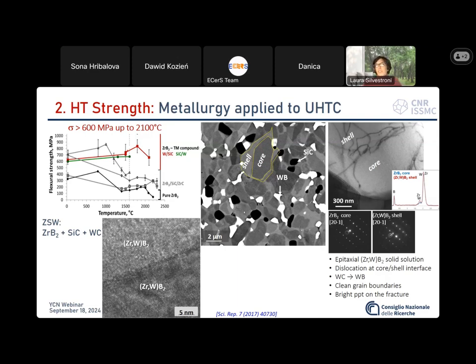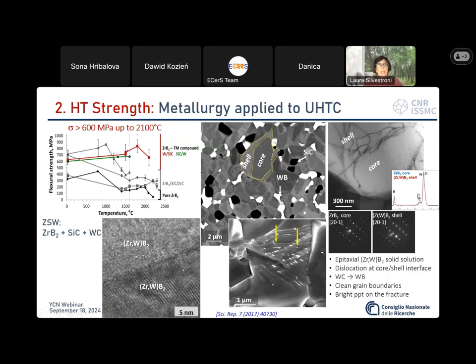As main microstructure features, it was fully dense with clean grain boundaries and a mean grain size around 1 micron, nothing special. The grains were featured by a core-shell structure with a pure zirconium diboride core and a solid solution around the core containing tungsten. Most of the tungsten carbide was converted into tungsten boride phase due to the reducing environment. And in addition, we noticed on the fracture surface that we detected these bright elongated particles and a zigzag fracture pattern.